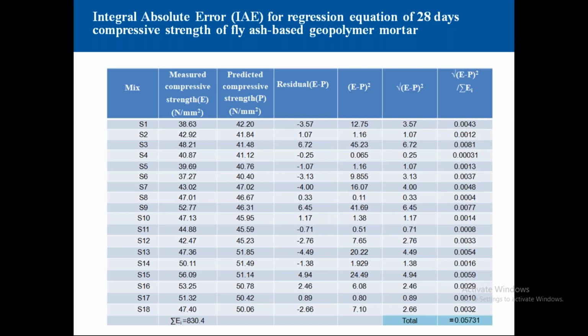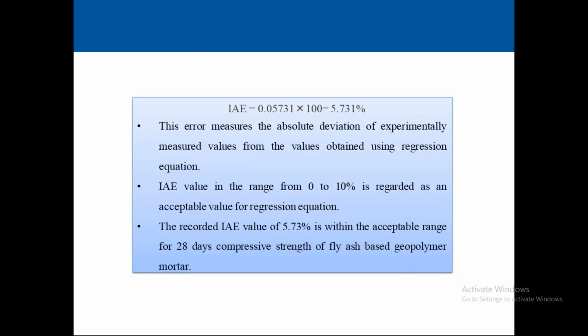Then depending upon those residual values, we can find the integral absolute error. And when we say integral absolute error, if it is less than 10%, it is always better. It is considered to be significant. So this error measures the absolute deviation of experimentally measured values from the values obtained using regression analysis. So the range of 0 to 10, as I already told you, is regarded as acceptable. Our value was 5.73%, so it is within the acceptable range.